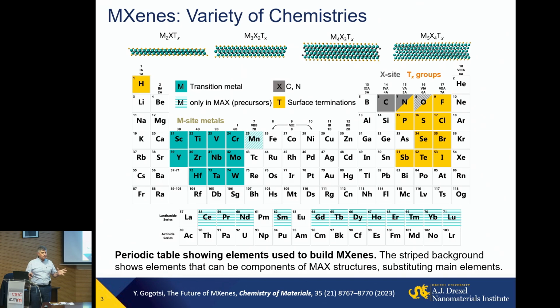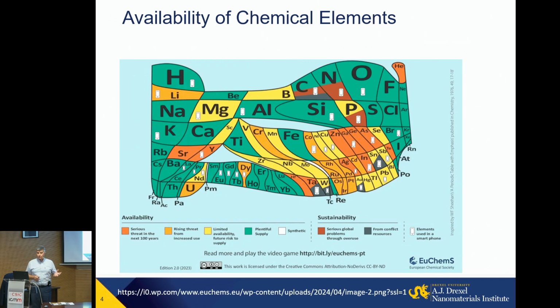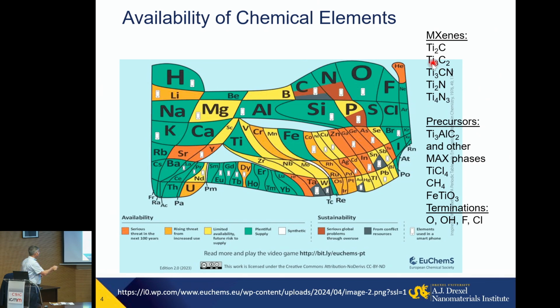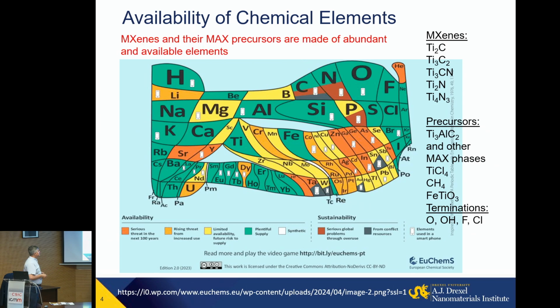Imagine, you can make 1,000 new materials, but moreover, you can mix and match on the X site, making carbonitrides, or on the M site, making solid solutions. So really, an infinite number of new materials can be made in this system. Moreover, many of them can be made of common and abundant elements, like, for example, titanium carbides, nitrides, carbonitrides. The precursors we use for them, and I will talk about them for selective etching, like MAX phases, contain aluminum or silicon or titanium. We can make them using vapor phase synthesis from, again, very, very common materials. What does it practically mean?